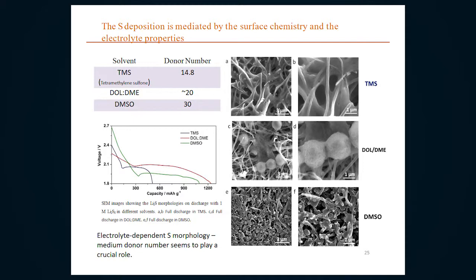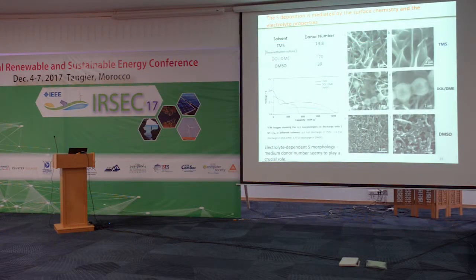That's the condition we have been trying to identify. I'm showing you a few examples where things work and where things don't work. You can have a situation where the sulfur only reacts with the electrode material and reversibly forms particles on the surface. That's a condition where things will work. But then you can have a situation where everything precipitates in the solution and forms just a few small particles on the cathode. That doesn't work. Or you have a situation where the whole surface is covered with a continuous layer of sulfur, and then you isolate the electrode from the electrolyte. That doesn't work either. Those are the things we need to work on in the sulfur system.